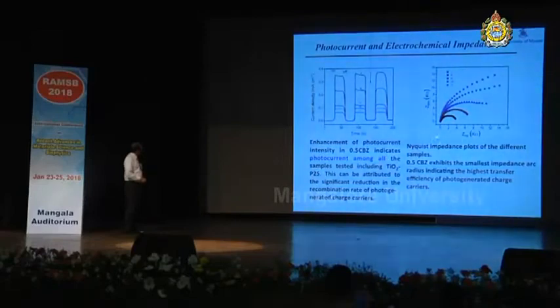And this is the Nyquist impedance plots for the different samples we have obtained. And this is the best one with this composition, 0.5 CBZ. And this shows the highest transfer efficiency of photo-generated charge carriers.